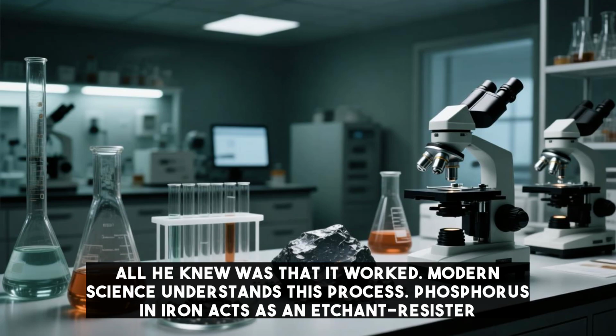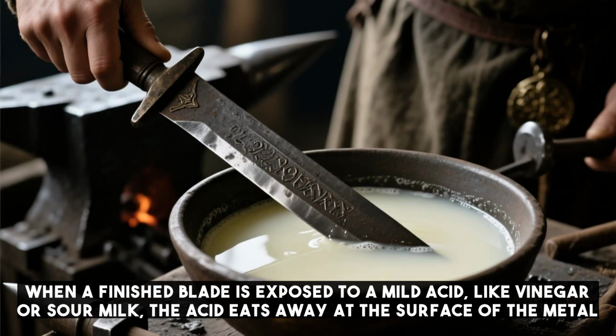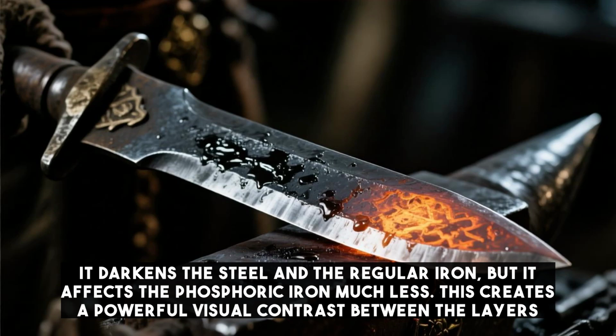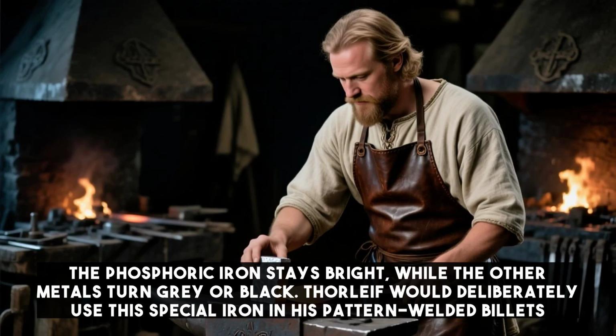Modern science understands this process. Phosphorus in iron acts as an etchant resistor. When a finished blade is exposed to a mild acid like vinegar or sour milk, the acid eats away at the surface of the metal. It darkens the steel and the regular iron, but it affects the phosphoric iron much less. This creates a powerful visual contrast between the layers. The phosphoric iron stays bright, while the other metals turn gray or black.